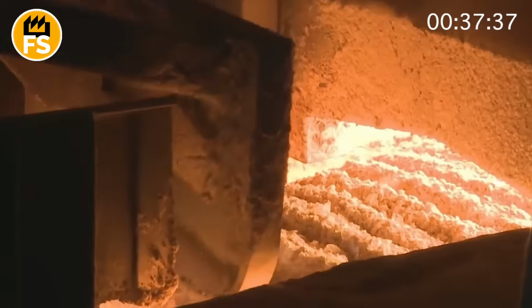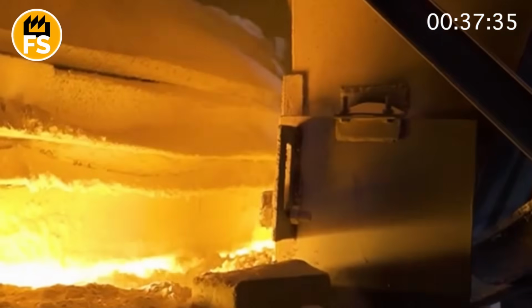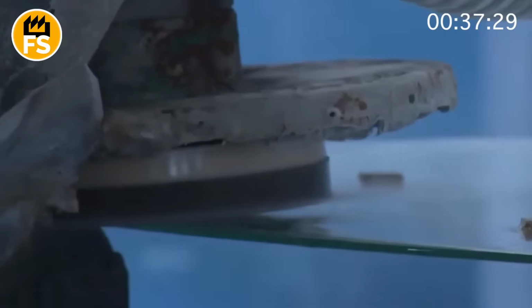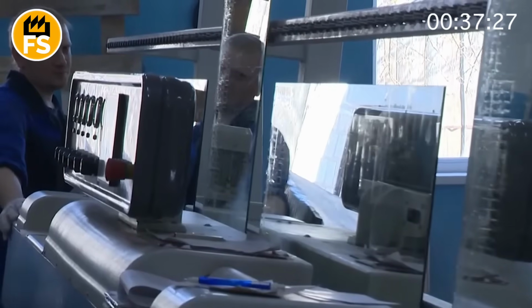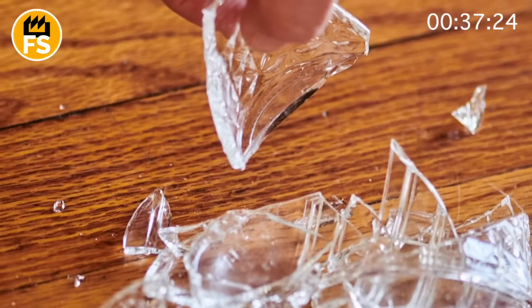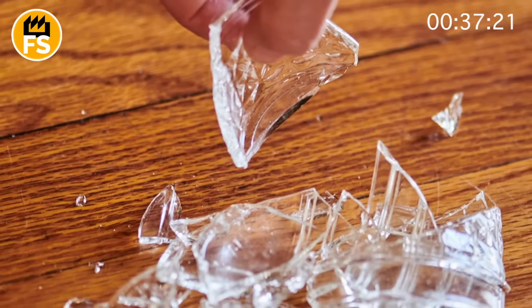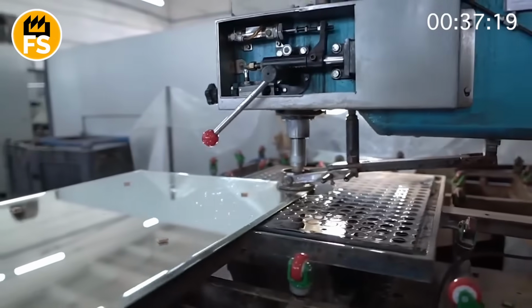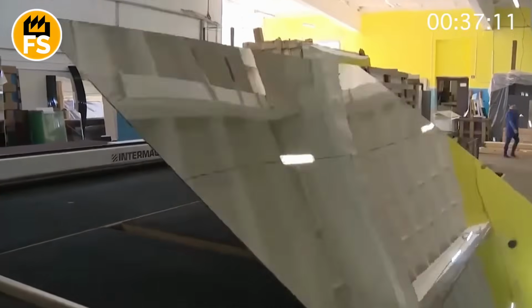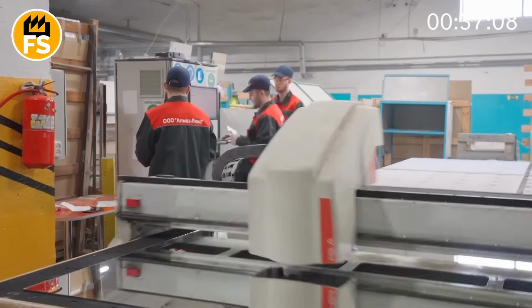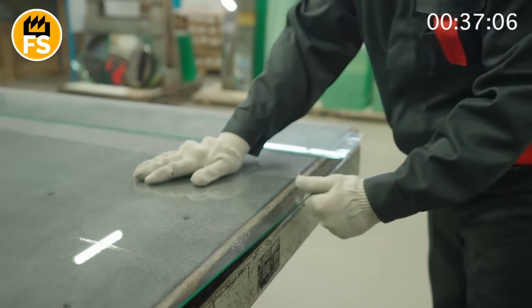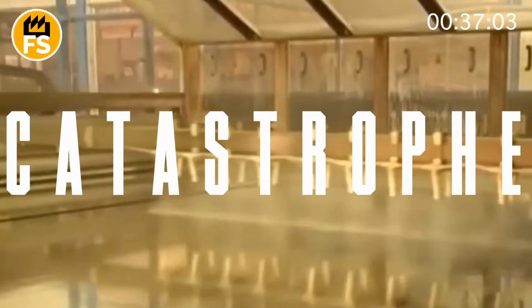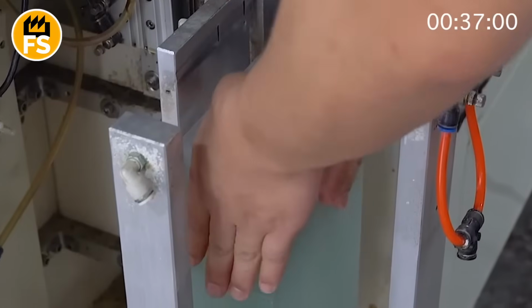Why such strictness? Because after the glass has gone through the furnace, it becomes untouchable. Trying to drill or cut tempered glass is a guaranteed way to instantly turn it into a shower of a million small, blunt cubes. Its internal stress is so great that any surface disturbance leads to an explosive release of energy. So, each piece is carefully prepared, inspected for the slightest defects, microcracks, or air bubbles, which in the furnace can become the epicenter of a catastrophe. And then it is washed and dried to perfect cleanliness.